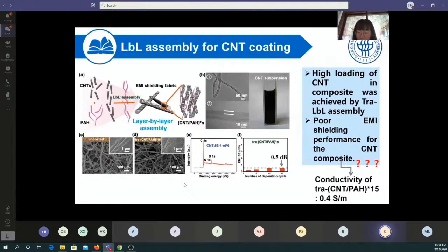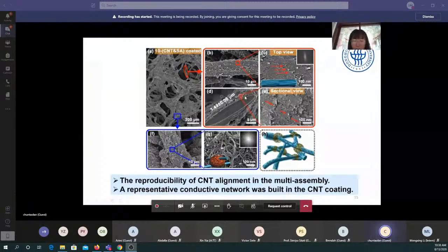Therefore, for the further study, we use the fabrics with 3 milligrams per mL SA to further study the performance of the fabric. After the first deposition cycle, the axially aligned CNTs were prepared, and they are well aligned with the axis of the fibers. The thickness of the coating is 1.5 micrometers, which is among the thinnest of conductive coatings. And we also notice that at the junction of two fibers, the CNT distribution is random.